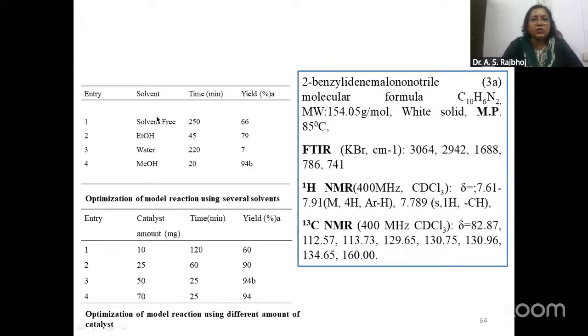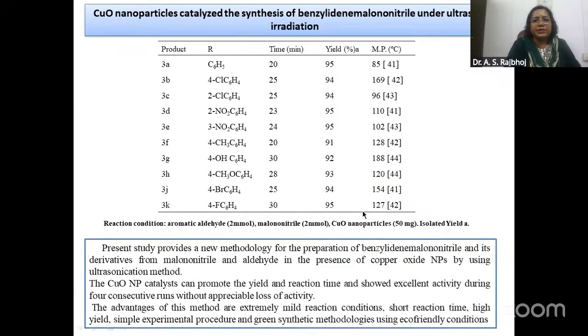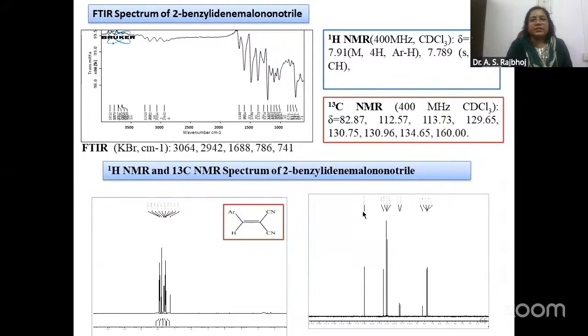This is the solvent-free medium, and ethanol, water, and methanol. We have used all these solvents, but using methanol we found that the time was less and the yield was much higher. The catalyst amount was also optimized. So 50 milligram catalyst gave us 94% yield, and we have done all the characterizations of our product, benzylidene malononitrile, by FTIR, NMR and C13, and these are the derivatives we have got. This is again the characterization of our product, that is IR, C13 and NMR.